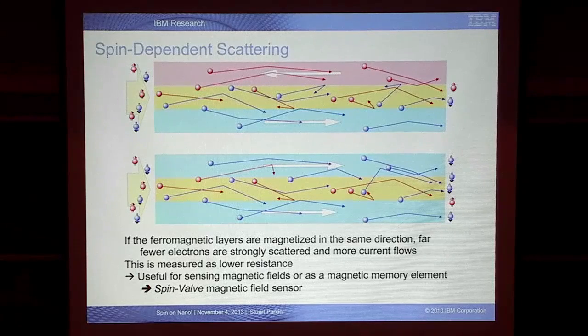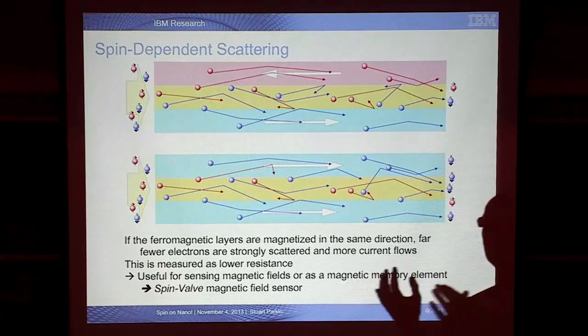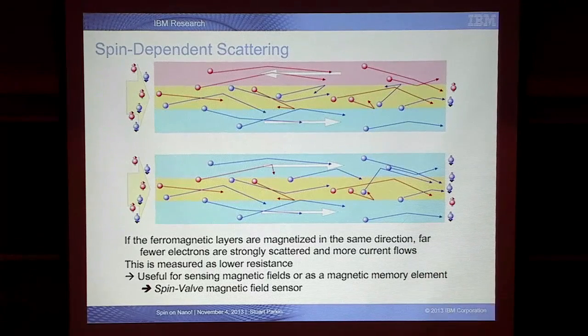We're not changing the orientation of any atoms. Each atom in this particular case is a magnetic atom. So in that particular atom, the electrons want to have their spins within the atom oriented parallel to one another. This is called an exchange interaction. And so each atom has a magnetic moment, and each atom then is magnetized in the same direction through this exchange interaction. So the block of material is magnetized together. By applying a magnetic field, we can change the orientation of all these magnetic atoms together. We're not changing the atoms themselves, just the electron spins, so they will be reoriented parallel to the field. Does that make sense? Sure, and you can do that quickly.